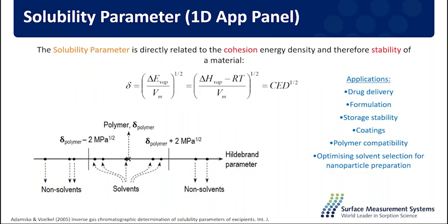The Hildebrand parameter just expresses the total solubility parameter. It also correlates with the cohesion energy density of the solid. And if you measure the Hildebrand solubility parameter of your polymer or your solid material, then it's very easy to determine which solvent will be the best choice and which will not, because based on the theory, the difference of plus or minus 2 megapascal root square tells you which solvent is the best. So anything which has a solubility parameter higher or lower than your polymer by more than 2 megapascal root square is not the best solvent.